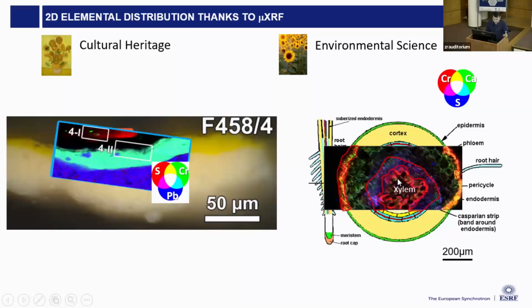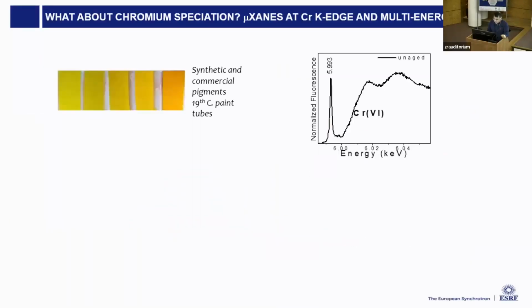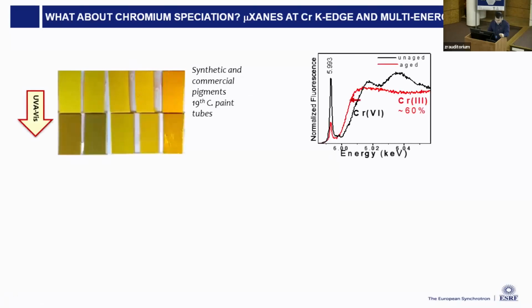However, only this information is not sufficient to conclude anything about degradation or toxicity. For that, it is fundamental that we assess the chromium speciation. To answer this question, we use X-ray absorption near edge spectroscopy at the chromium K edge. Here, I focus on the painting samples. Originally, chrome yellow is made of chromate, but under artificial aging, in some conditions, chromates can reduce to chromium 3, which explains the browning of the paintings. We observed a similar structure in historical paintings, right?